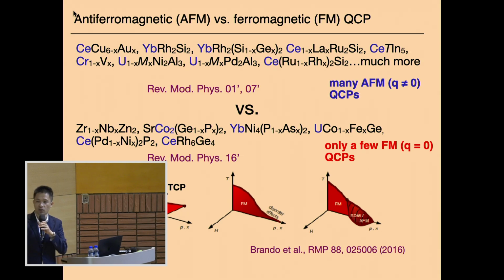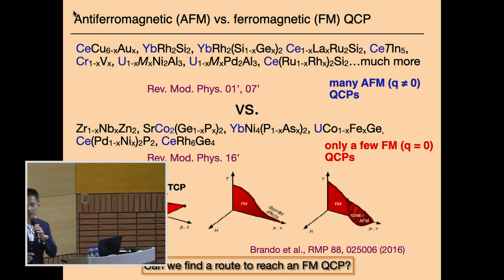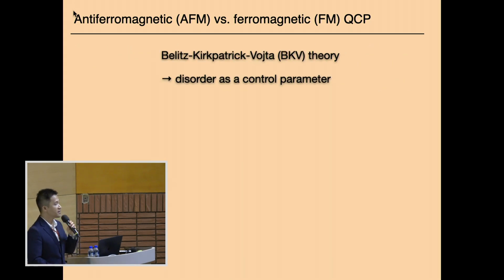And if you apply field, you will form this fishtail-like phase diagram. And when people try to use disorder, chemical substitution, to tune the system, sometimes the disorder effects are too strong that the phase boundary will be smeared out. So again, there's no QCP. And sometimes it's even more exotic. The magnetic ground state changes from ferromagnet to antiferromagnet. So my question is, can we find a route to reach an FM QCP? That's my motivation. And the answer is probably yes.